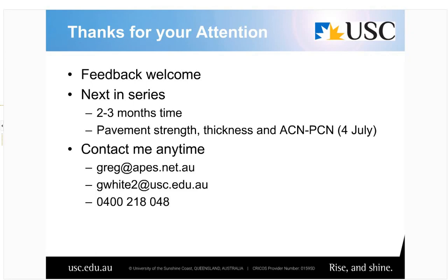Just before we finish that off, Josh has also asked about maintenance rolling and the use following construction to keep the bitumen lively, which is another good point, and certainly something in the details. But my advice to airports: if you build your seal well and you want to get 10, 12, maybe even more years out of it, instead of getting maybe 6, 8 or 10 years out of it, then one of the best things to do is to re-roll it every year.